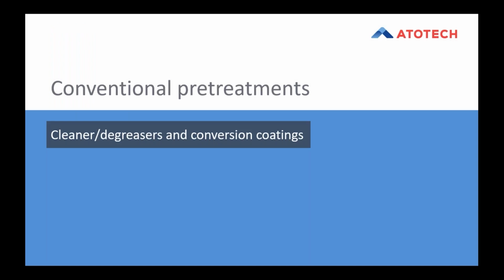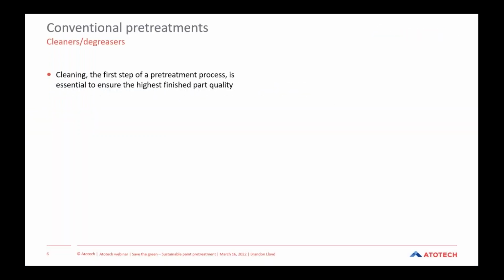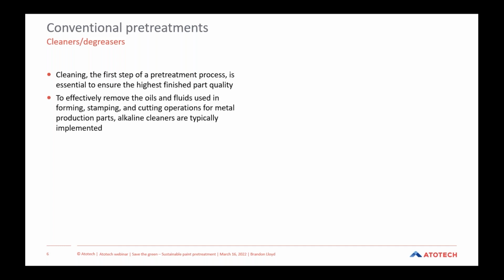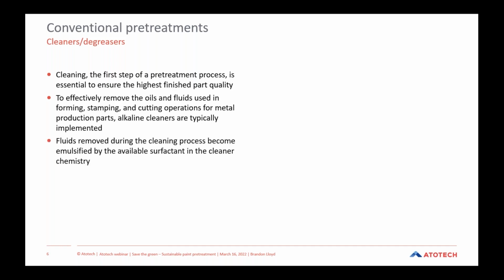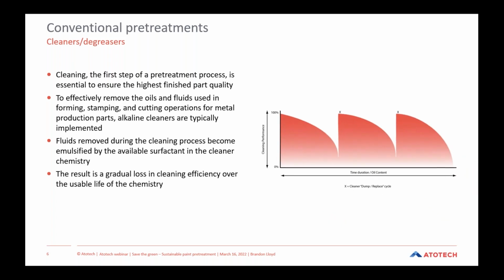So starting first with conventional pretreatments. As we know, cleaning is the essential first step for any good pretreatment process and really is critical to ensure the highest finished part quality. To effectively remove the oils and fluids that are typically used in forming, stamping, and cutting operations for metal production parts, applicators traditionally use an alkaline cleaner for these processes. The fluids that are removed during the cleaning process become emulsified by the available surfactant in the cleaner chemistry itself. The result is a gradual loss in the cleaning efficiency over the usable life of the chemistry.